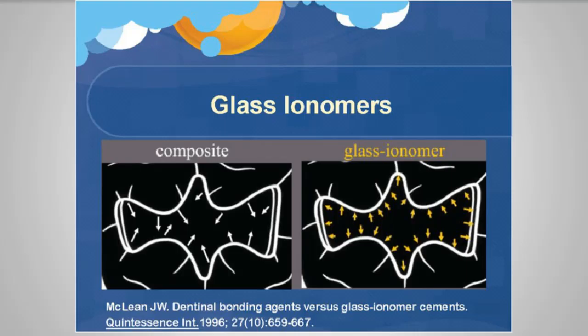That's where your sensitivity comes from when you dry the teeth too much when you're using GIs and resin-modified glass ionomers. You need it slightly moist. You need it glistening a little bit so that there can be an integration to the tooth structure and the absorption of the water from that to help the overall structural work well. So that's another important thing.